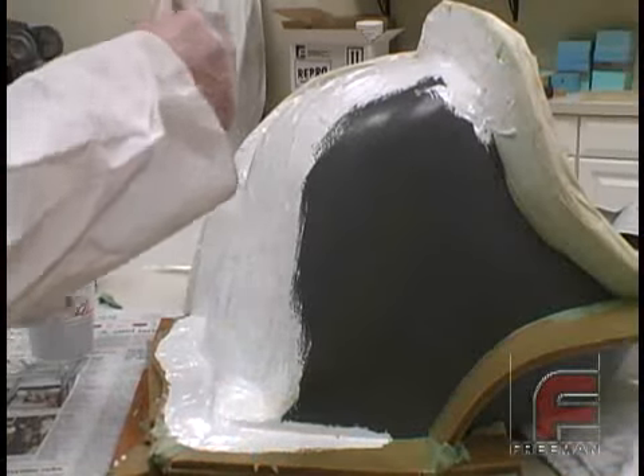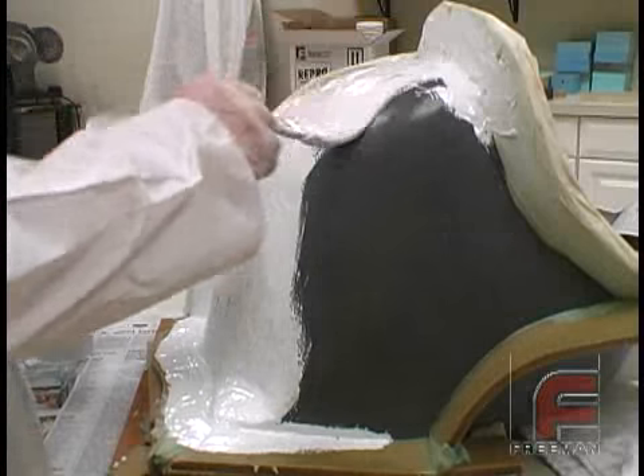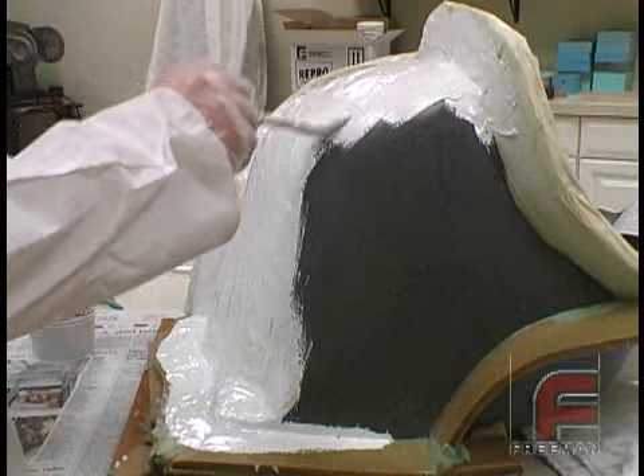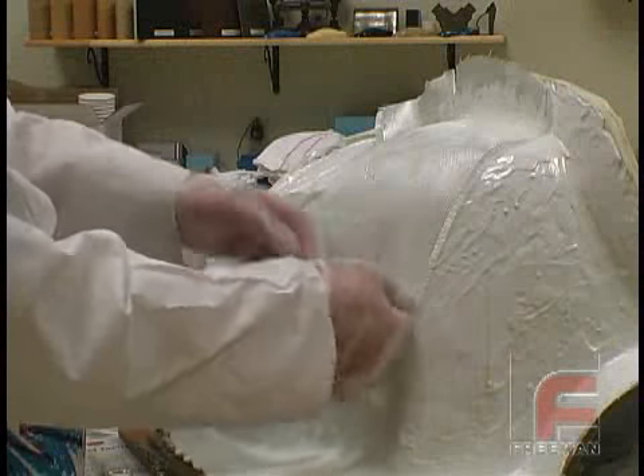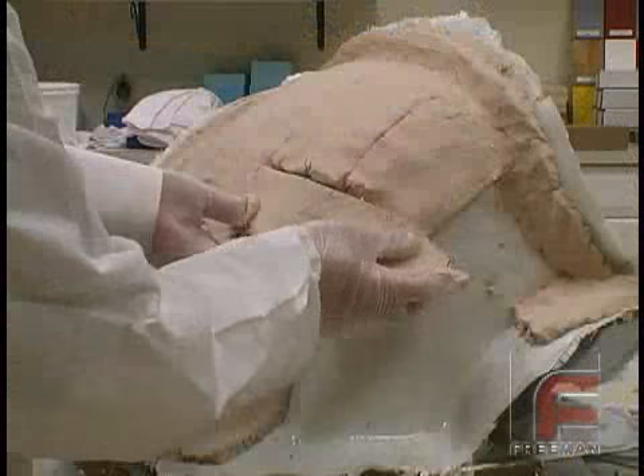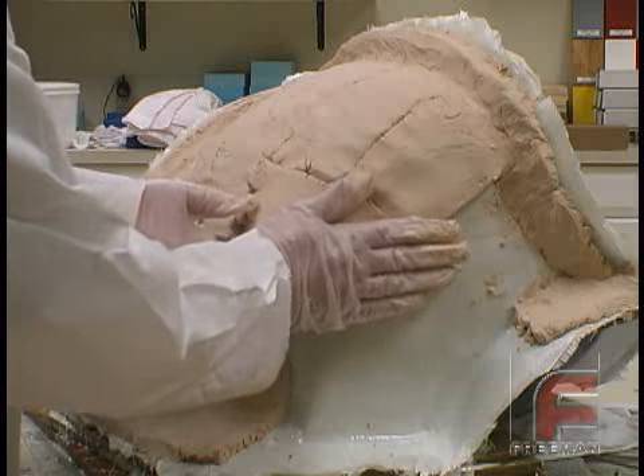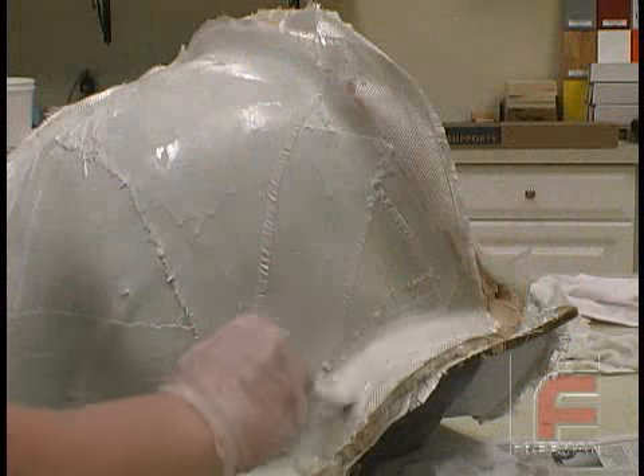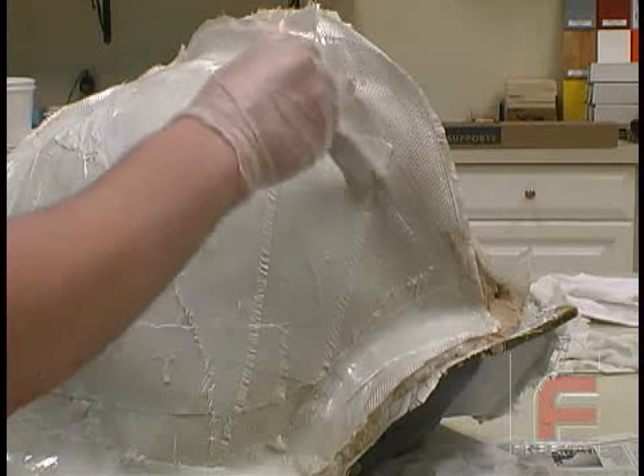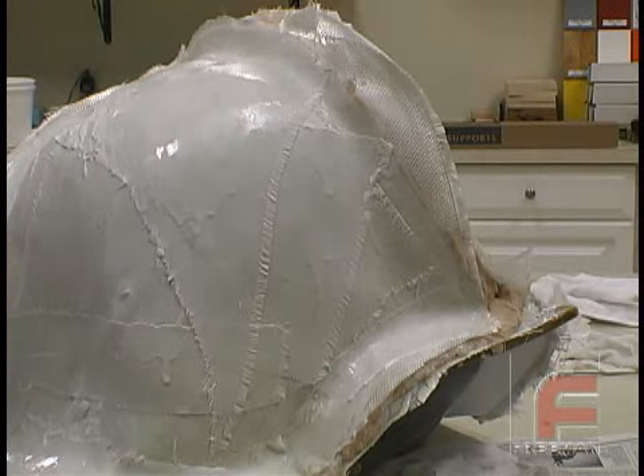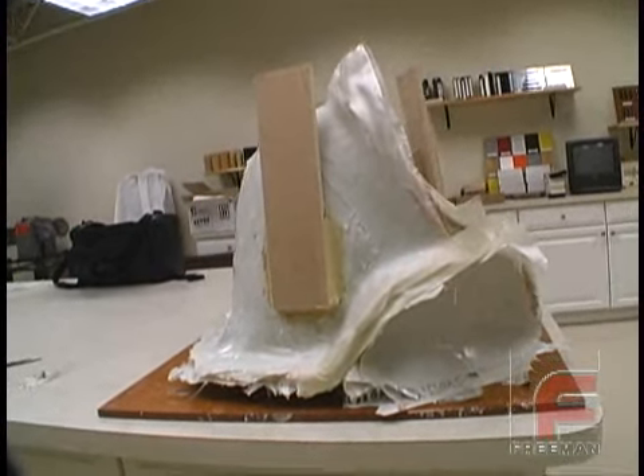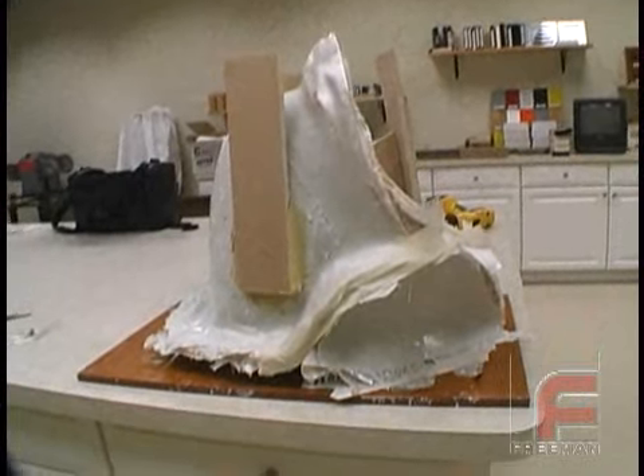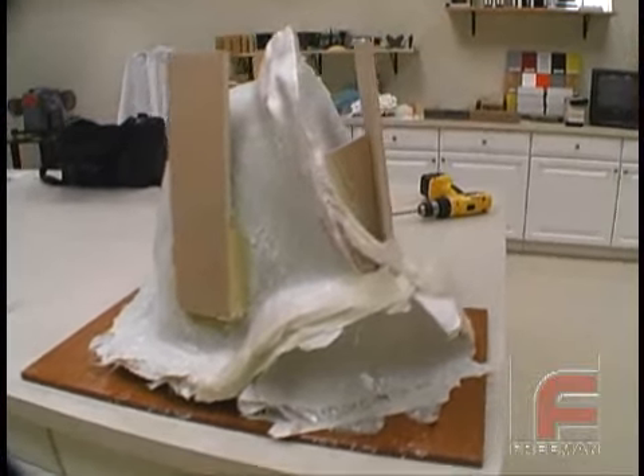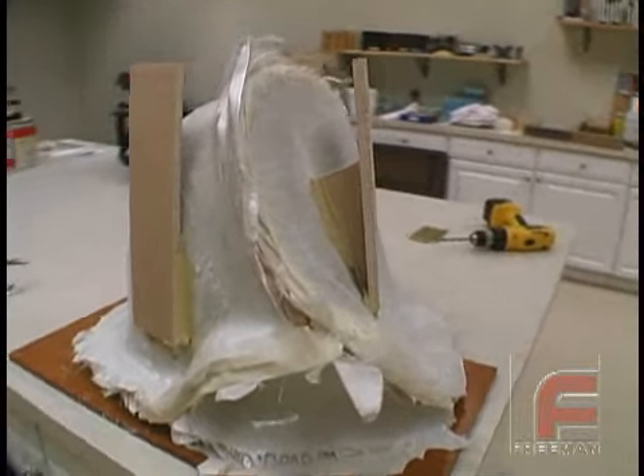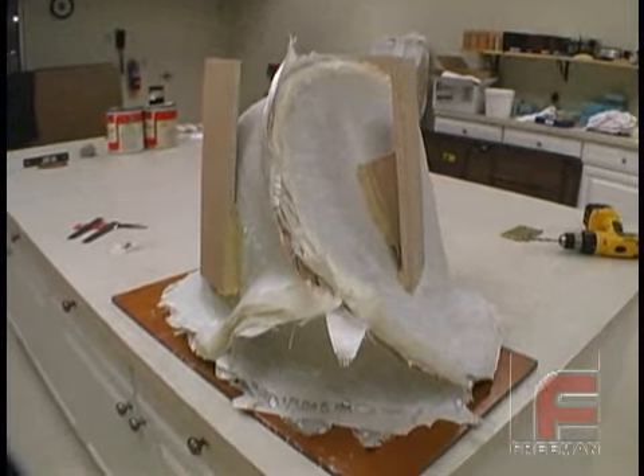The remainder of our paste laminating is exactly as we did the day before, applying two layers of surface coat, three layers of fiberglass cloth, our half-inch thick layer of paste laminate, and finally our last three layers of fiberglass cloth. On the third day, we created our third part just as we did parts 1 and 2, and here on the fourth day, our tool is complete and we're ready to demold. Notice the makeshift stands that we have attached to the outside using our tough fill. This is so we can later turn the tool upside down.